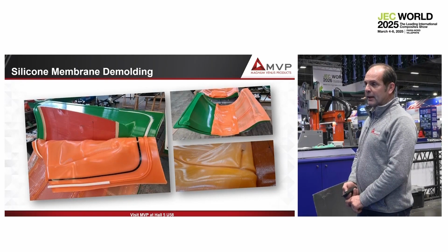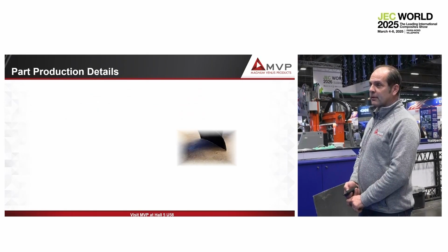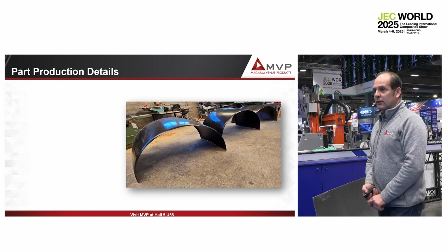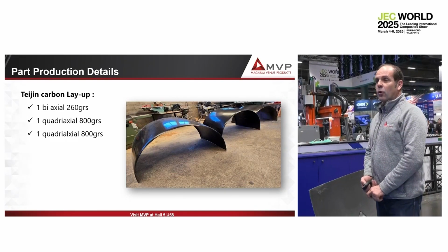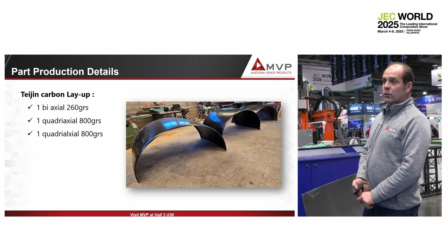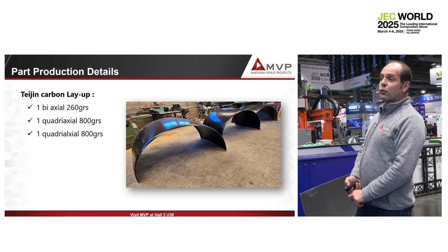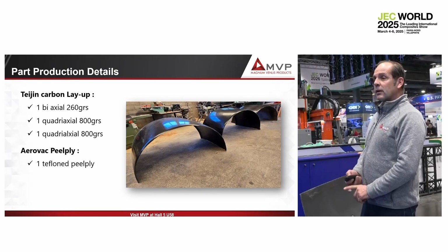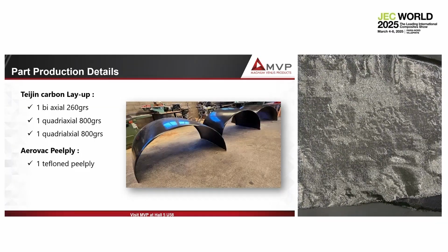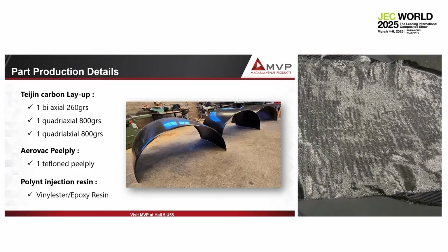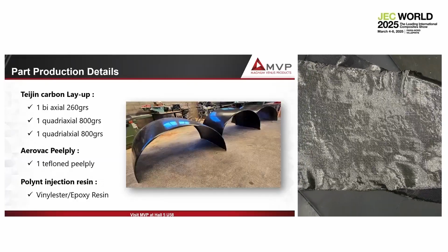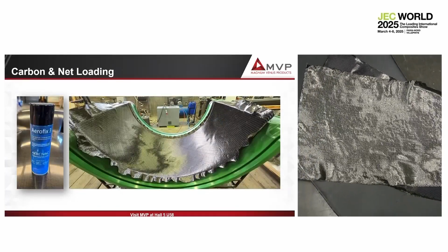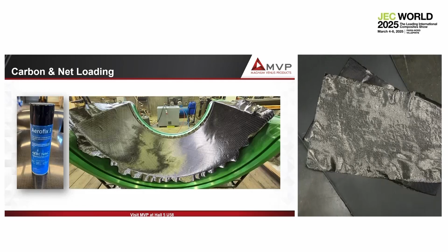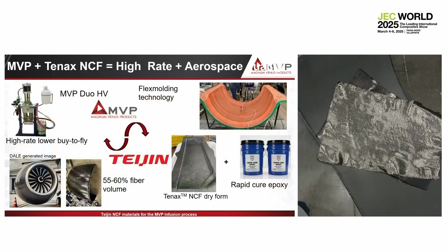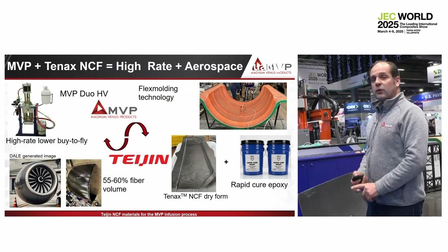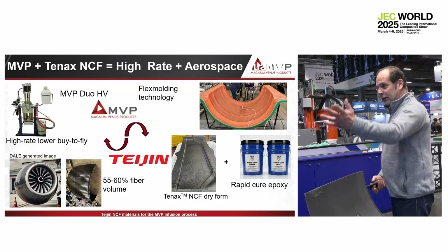So we demold the bag, we test the bag with the channel, and now these are the part production details. So we have 1 biaxial, 260 grams from Teijin, and 2 quadriaxial. And then on top of that, we put a Teflon peel ply, and we use the Polynt resin to inject the part, vinyl ester resin. So for that, we load the carbon with the Aerofix. And I will let my colleague Alfonso talk about the Teijin fiber.